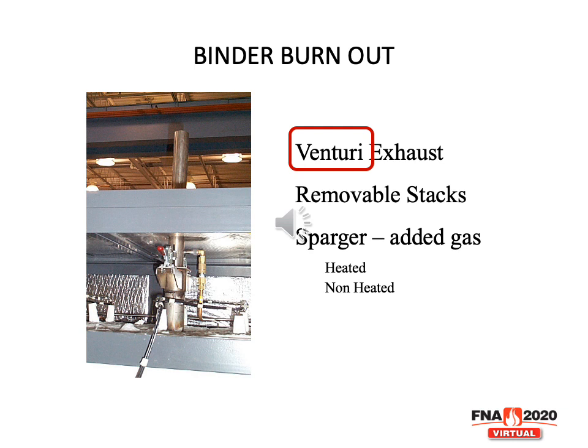We actually had a furnace at one point in time that was used for copper end termination, where we needed to run maybe 10 or 15 ppm of oxygen for the binder burnout section. We used a lot of sparges and added some gas in there to keep that mixed up. Then following just after that, without gas barriers, we were able to run down to less than 2 parts per million during the sintering section when we raised the temperature. That was a very unique machine. It was a lot of fun to run.